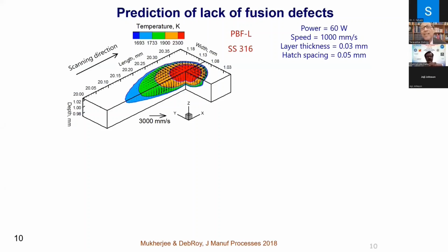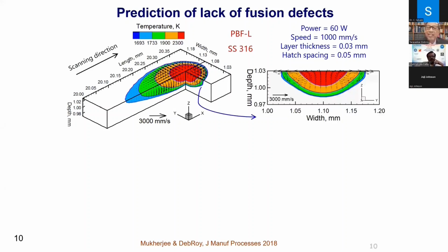So let's take lack of fusion defects. And we start with what we just calculated, temperature and velocity fields for making a part out of stainless steel 316 using thin layers of powder bed. 60 watt power, about 1000 millimeter per second, and we are making very thin layers, 0.03 millimeter. Sometimes we make these layers thinner than a human hair, and we have parallel deposits that we call hatch spacing, 0.05 millimeter. If you take a cross section, they look like you have just cut a watermelon in half and sectioned it.